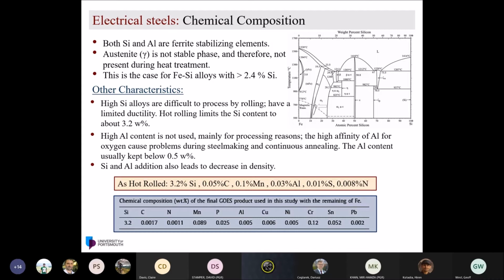Now, the advantage of aluminum and silicon is that they are both ferrite stabilizers. If you look at the phase diagram of iron and silicon, you will see that if you add anything above 2.4 silicon, I'm avoiding austenite. If I draw a straight line, anything above that, I'm avoiding the austenite formation, even above 1200, 1300 degrees Celsius. And that's giving an annealing window.